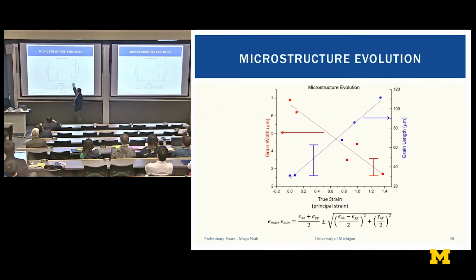Fortunately, what Maya found was, at least in the specimens we've been looking at, the grain structure changes proportional to the sheet elongation. So we didn't really find any surprises there. We do think at some higher deformation we're getting some recovery and recrystallization, but basically the grain size is mirroring the stretching of the sheet.